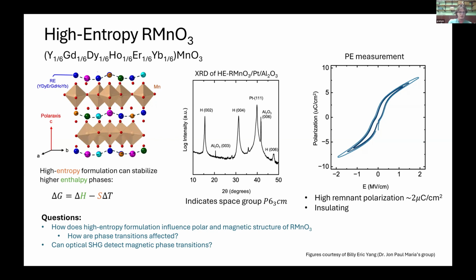People have had success with this in multiferroics, for example, in rare earth ferrites. So our collaborators in Dr. Maria's group synthesized thin films of these. They did XRD and confirmed this is space group P6_3cm, so this is hexagonal like we expect. The PE measurements, the ferroelectric characterization, are rather promising because we have high remnant polarization, and these are insulating, where most ferroelectrics tend to be fairly leaky.